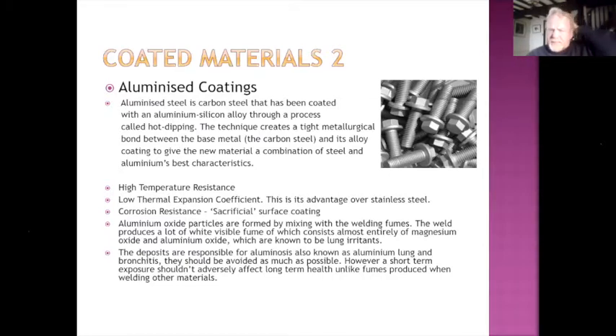When it is welded, some of the particles could actually produce light fume, which consists almost entirely of magnesium oxide and aluminium oxide, which are known to be lung irritants. The deposits are responsible for aluminosis, also known as aluminium lung, and bronchitis. These should be avoided as much as possible. However, short-term exposure shouldn't adversely affect long-term health, unlike fumes produced when welding other materials.